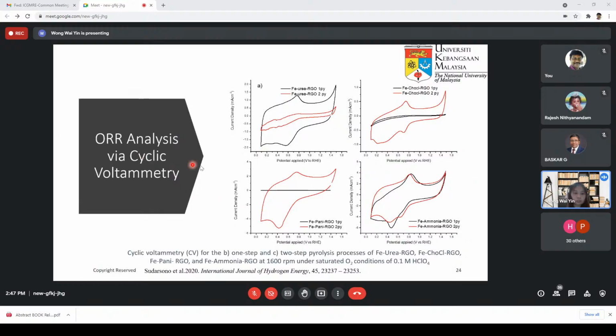Now, if we move on to the ORR analysis, with the cyclic voltammetry, we examine the ORR activity for first pyrolyzed and second pyrolyzed samples. You can see that here, this is basically the ORR peak, the oxygen reduction peak potential. Okay, so for urea, after second pyrolysis, it doesn't show any improvement. For choline chloride, yes, it shows some improvement, but mainly these peaks belong to the Fe peak, and this reduction potential is pretty low here. While for Fe-PANI, with first pyrolysis, it shows inactivity, but upon second pyrolysis, it shows a very apparent reduction peak here and very high current density obtained. While ammonia-wise, there's not much change, okay, in comparing first and second pyrolysis.